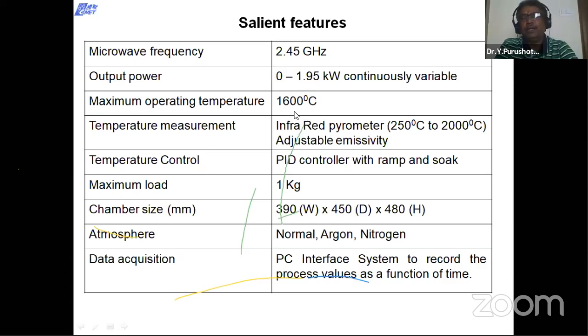And one can obtain 1600 degrees centigrade as the maximum temperature, but I operated up to 1500 degrees centigrade. And this is the pyrometer, range from 250 to 2000, because our requirement is high temperature. There are different types of pyrometers available with adjustable emissivity, and this is the range. Below 250, it shows only 250, whether it is room temperature or 249. Because our requirement is high temperature, that's why we selected a pyrometer in this range. And the temperature controller is PID.